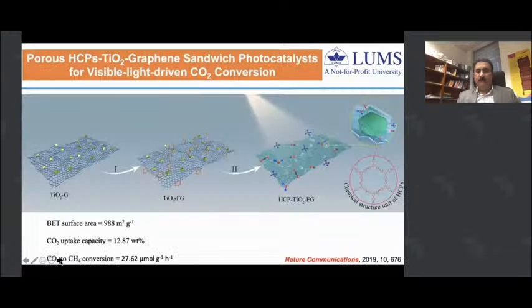Moreover, even more recently, mainly by Professor Bian Tang's group, we coated titanium nanoparticles with these microporous hypercross-linked polymers and then immobilized them on graphene oxide. So, for example, carbon dioxide can diffuse through these microporous polymers coated on titanium nanoparticles, and guide them to the titanium nanoparticle surface, where they are photochemically converted into hydrocarbon fuels.